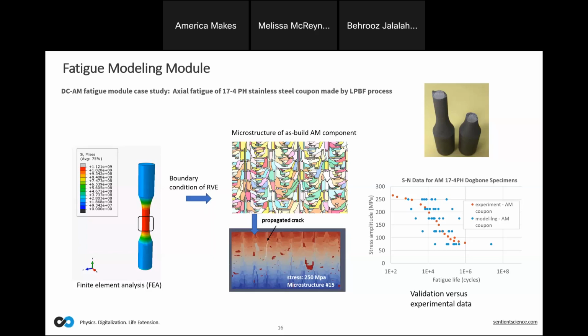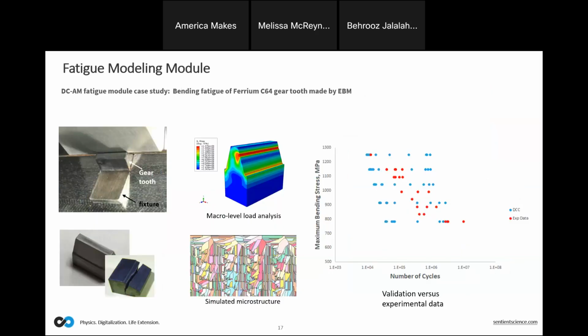The reason for that is that as we are doing the simulation, the microstructure that we are creating goes from the worst case scenario to the best case scenario: what would happen if you are not lucky and your microstructure is the worst that it could be, and what would happen if it is the best that it could be. And as you can see, the experimental behavior is right in the middle of that range. Go to the next one, please.